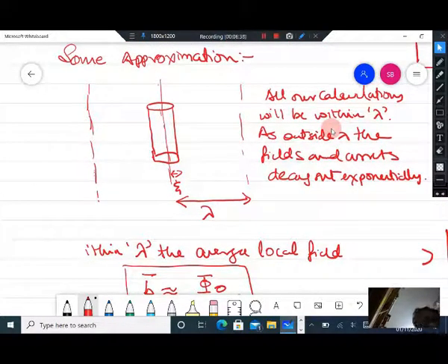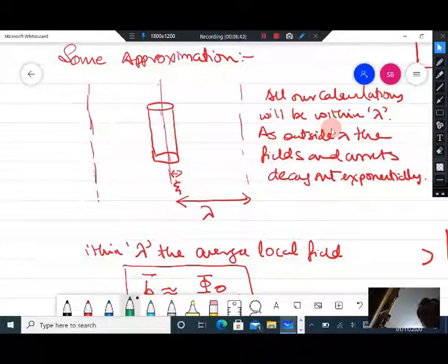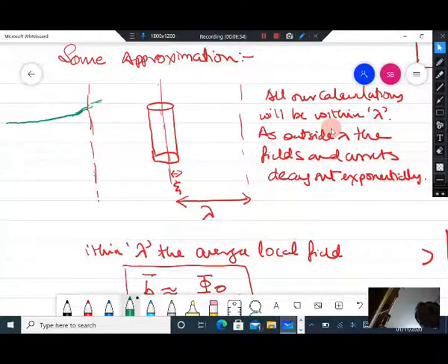And this is roughly true because at a distance outside lambda, the flux is decaying exponentially, it is exponentially small, and then it becomes roughly constant. So it decays exponentially, and then here it is actually varying logarithmically, it is changing very slowly, and then over the vortex core it becomes constant. So the flux change is very weak.